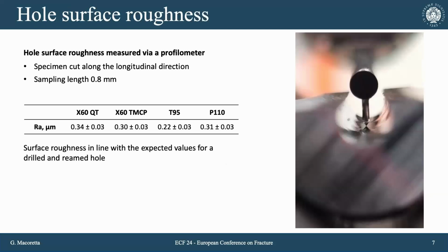Let's start with the assessment of the surface integrity of the hole. The hole, as I said before, was produced by drilling and reaming. So we carried out some surface roughness measurements on the internal hole of the specimen, and the results are in line with what we can expect from a reaming process. We have an average roughness value of 0.3 microns, which is in line with the reaming process.